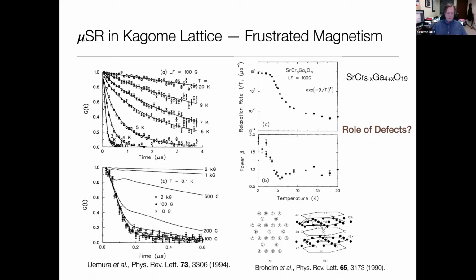In fact, back in 1994, even back when I was a postdoc, we were looking at this in early muSR experiments. And this is a system which again has a gradual slowing down of the spin fluctuations, and they tend to persist to the lowest possible temperatures. And so this material has been postulated as a possible quantum spin liquid example. However, it turns out that this material is not a perfect Kagome. So though you have a beautiful Kagome lattice, there turned out to be some magnetic defects in here